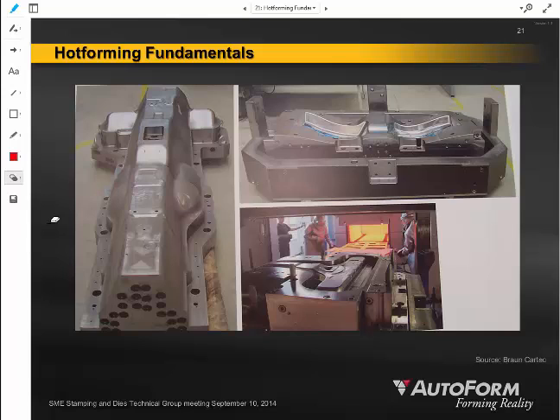They had two patents they were going for at that university. One was for the induction heating element design, and the other was for the fact that, in order for the induction heating to work, they had to come up with a new way to move the blank through the line. They designed an innovative walking beam automation mechanism as opposed to a conveyor belt in order to maintain the appropriate induction behavior. It was really, really cool what they were doing. So yes, selective heating would be another way of achieving that tailored behavior of strength where you need it and not where you don't. Absolutely, good comment. Thank you, Bob.